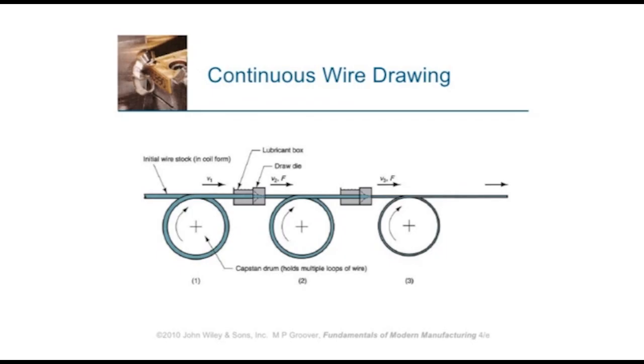The pointed end of the coil is placed in the drawing machine and loops around and is drawn along with a capstan, C-A-P-S-T-A-N. The capstan not only draws the wire through, but regulates the speed and tension of the operation. Between each capstan is the die in a block. The die reduces the diameter of the rod, shapes, and elongates it. There is tremendous friction caused by physically altering the rod and making it smaller.